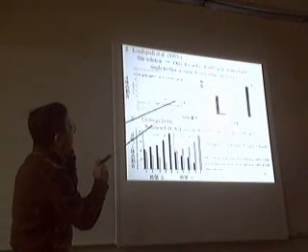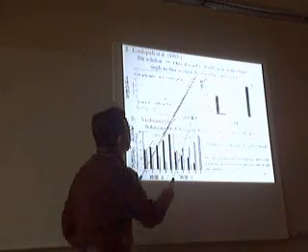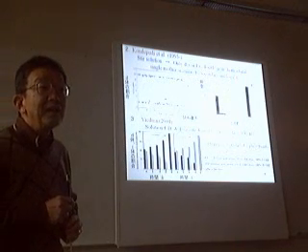So the interpretation was that the single mother crystal was nucleated, and by the stirring it was broken into small fragments, and secondary nucleation takes place.